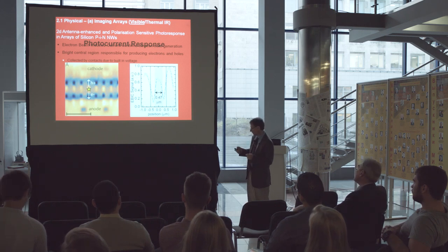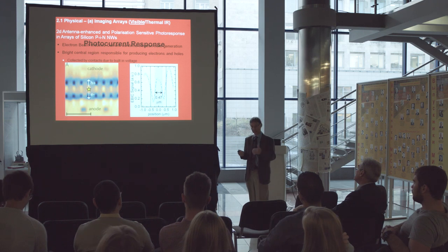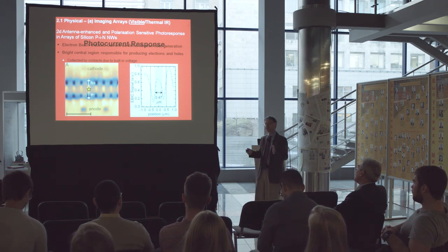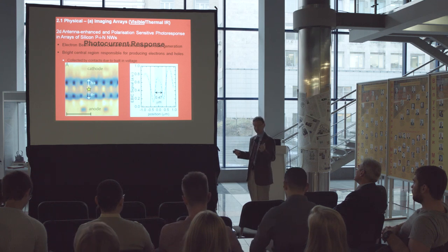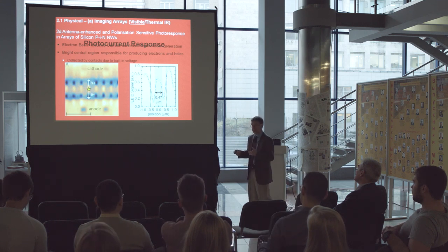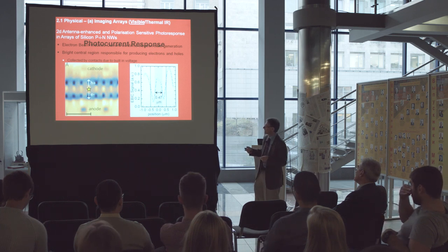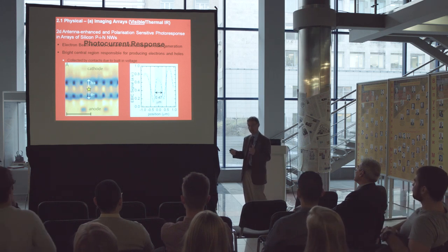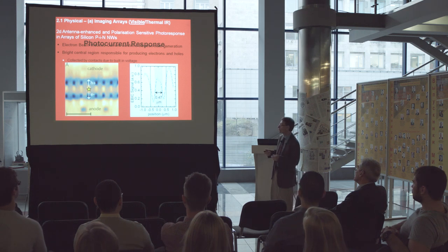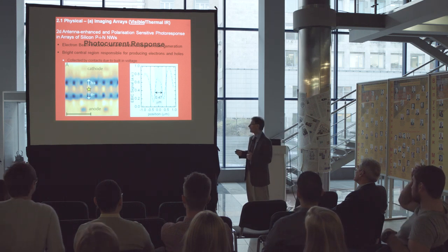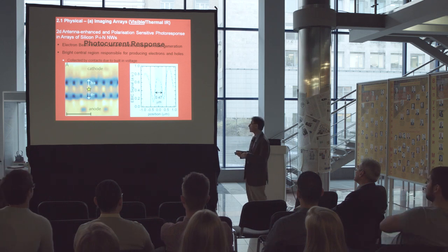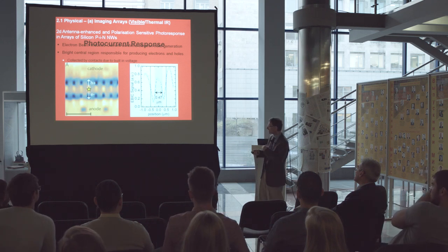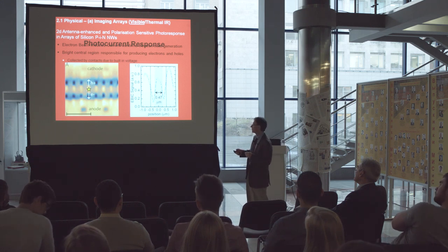In our case here, we're exciting with an electron beam, scanning, and synchronously measuring the current response of the device through a null amplifier to ground. We're doing this at low temperature, actually, which I didn't mention. This is at 77 Kelvin. What you're looking at here is the contact region, the central region with the electric field, and the contact again. You can measure the separation of charges by this image, and it tells us how well this thing is performing. We can do this under different biases and different carrier concentrations to understand how to engineer these things. So that's one of the techniques we use for feedback, apart from the optical response measurements.